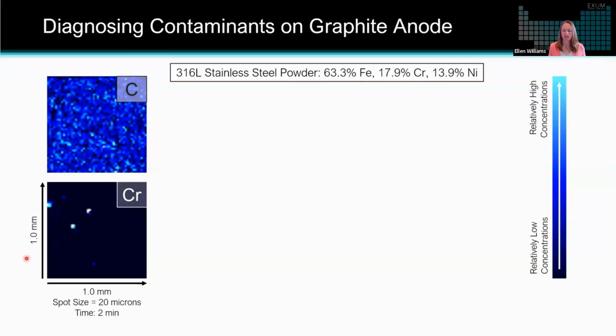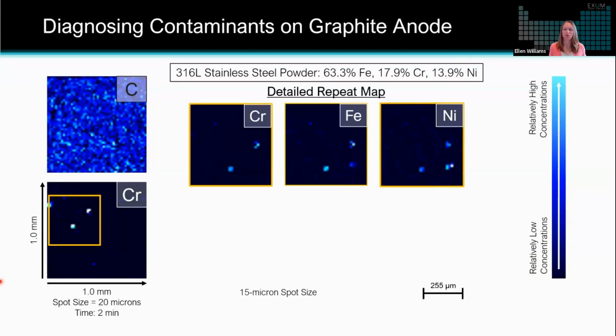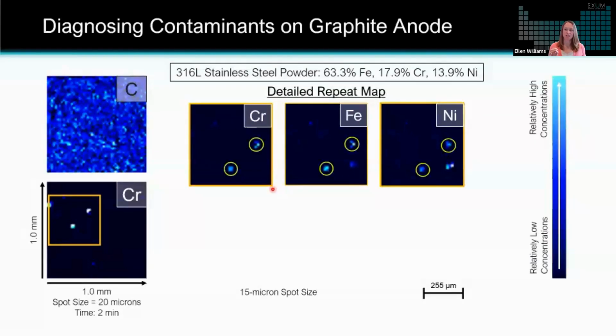But what we identify on the chromium map is a couple of discrete areas with relatively high concentrations shown in those brighter blues. So what we did was, again, a secondary map with a smaller spot size and higher resolution. So in this case, about a 0.5 millimeter by 0.5 millimeter area with a 15 micron spot size. And we can very clearly see that there are 2 distinct particles with high chromium, high iron, high nickel that correspond to that expected chemistry of these 316L stainless steel powder particles that we knew were on this graphite anode. So this demonstrates the technique's ability to reliably measure the chemistry of contaminant particles.